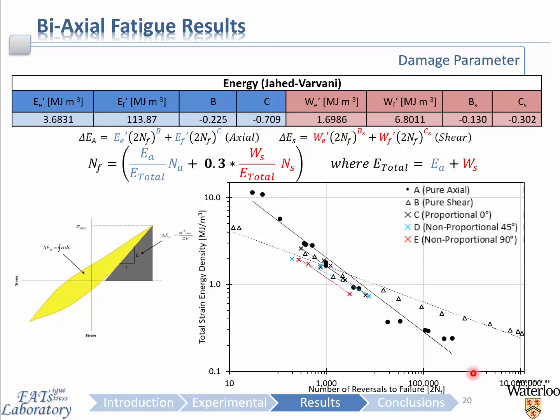The model is quite simple in that the life prediction is just a weighted average of the axial and shear fatigue life predictions that were calibrated from the energy life curves for each of the uniaxial cases. This individual weighting factor of 0.3 here places more emphasis on the axial energies being more damaging, as it's kind of artificially penalizing the shear direction, since the axial direction dominates the biaxial response, as well as the crack orientation, which I'll discuss in the subsequent slide.